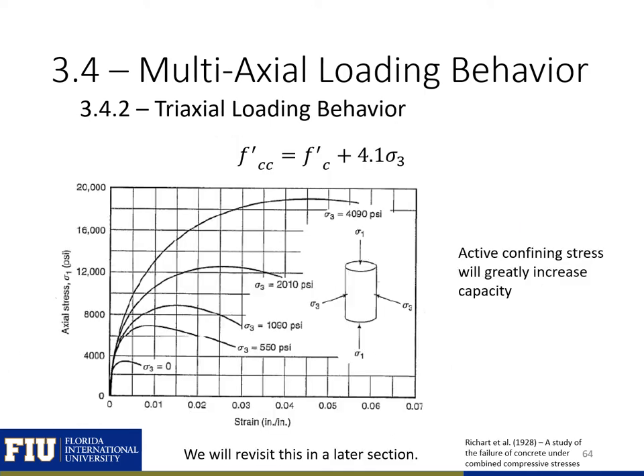Richart et al. proposed an equation to account for the benefits of transverse compressive stresses based on experimental testing. They found the compressive strength will increase by 4.1 times the active confining stress applied. You can see in their test results that adding 4,090 psi of confining stress increases the compression strength from around 3,800 psi to almost 20,000 psi. Confinement will greatly improve the overall behavior of the concrete. We will look at confinement more in depth later in our class.